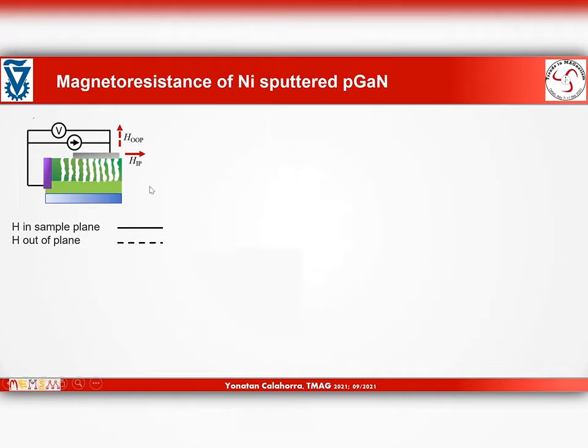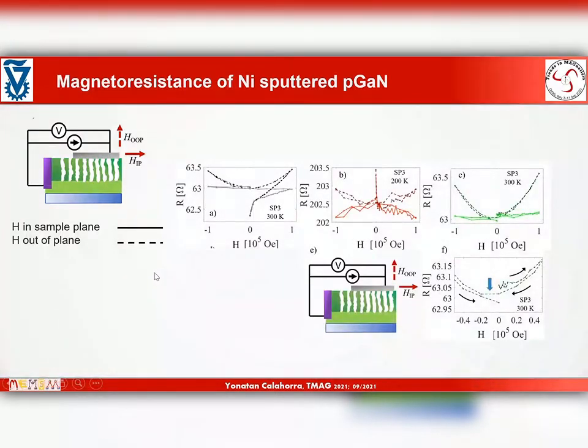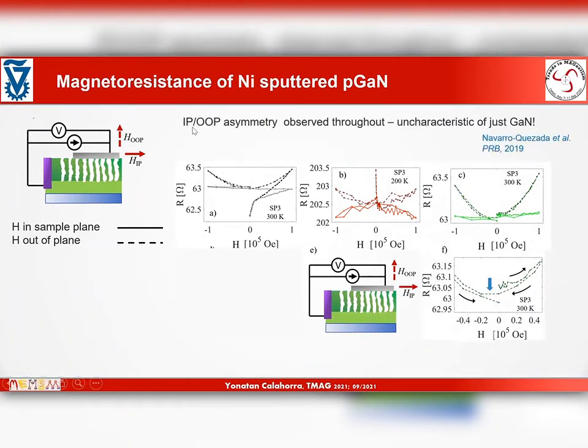Next, if we look at the magnetoresistance of such samples, although this time with a thicker nickel layer, about 200 nanometers, we carried out a series of magnetoresistance measurements, starting at 300K, going back to 200, and then moving back to 300. So the first thing we notice is that at room temperature, the magnetoresistance is positive, and that's uncharacteristic of nickel. We also notice that there is in-plane, out-of-plane asymmetry, and that's uncharacteristic of pure gallium nitride. So we realized that the conduction here is actually quite interesting, and something is going on here. We see a low field increase, and then this significant difference between the in-plane and out-of-plane magnetoresistance.